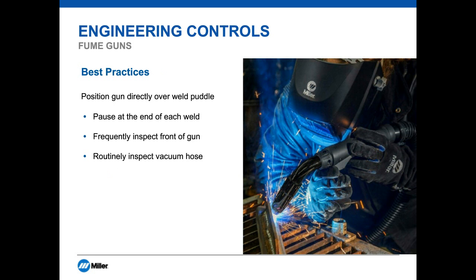Some of the best practices with a fume gun are positioning the fume gun over the weld puddle, making sure that you have that 90-degree angle to capture the fume. Pausing at the end of each weld is good to make sure you capture all the fume that is there after the welding process is completed. Frequently inspect the front of the gun for damage or buildup that could affect the capture at the tip. Routinely inspect the vacuum hose for any cuts or tears that could negatively impact the flow of the fume gun.